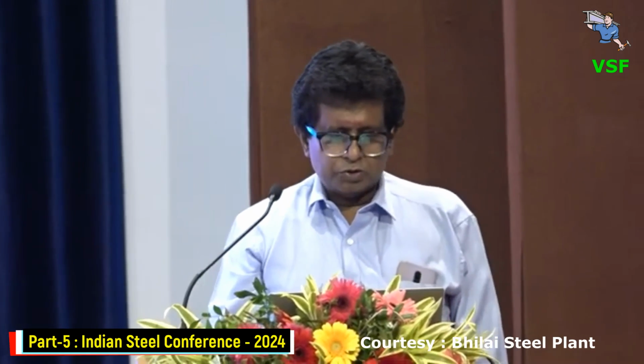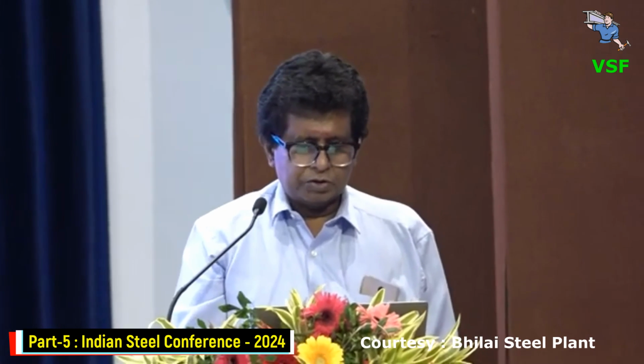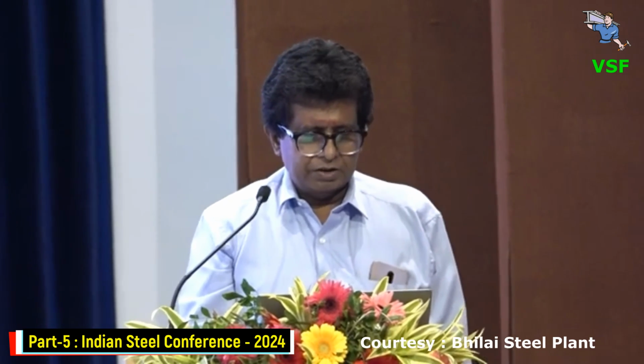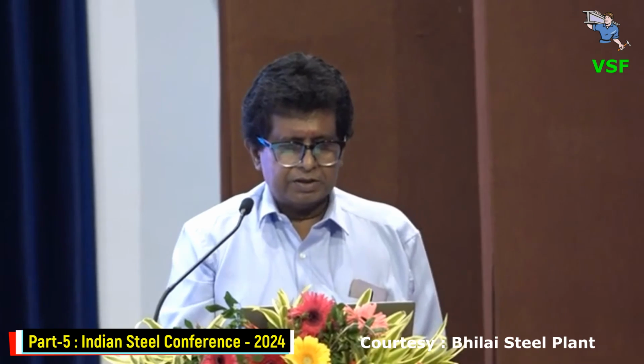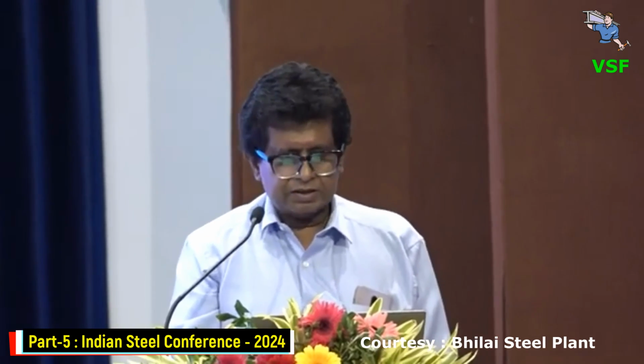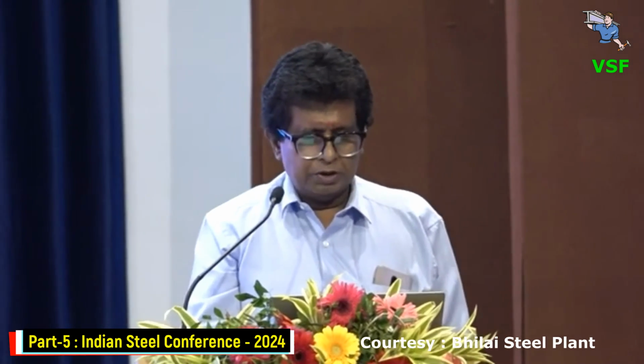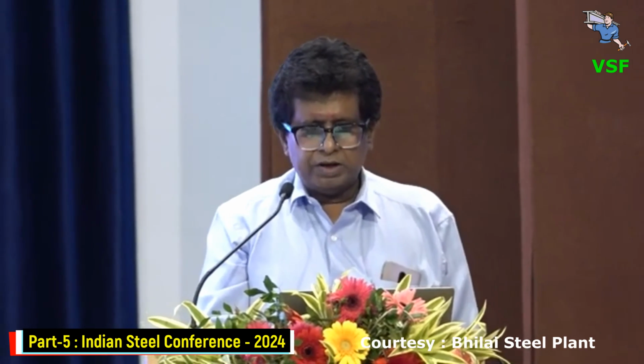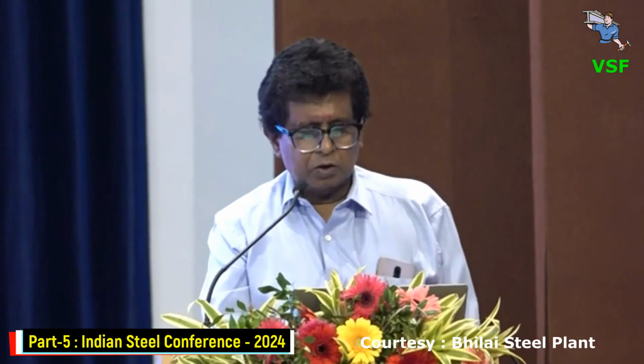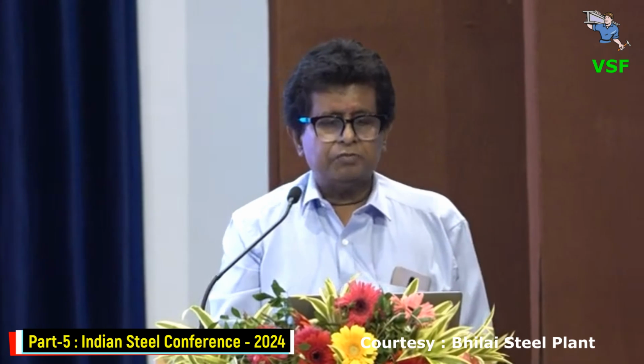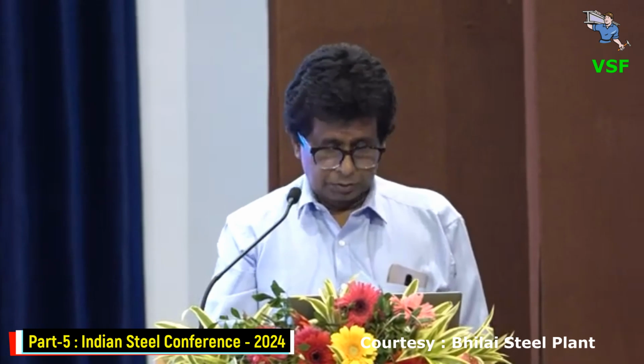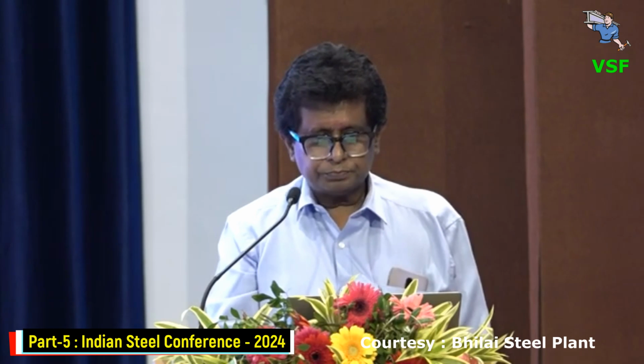And other carbon sources will be needed for FeO DRI reduction, foamy slag, all those parameters that have to be taken care of in any case if you want to produce steel in the EAF. Then you would be requiring a vigorous bath stirring. Because of less carbon, the churning of the bath will be supposedly less, so you need artificial bath stirring from the bottom.